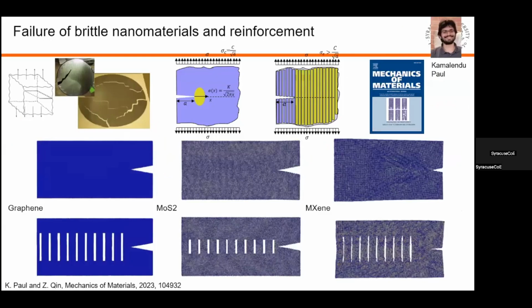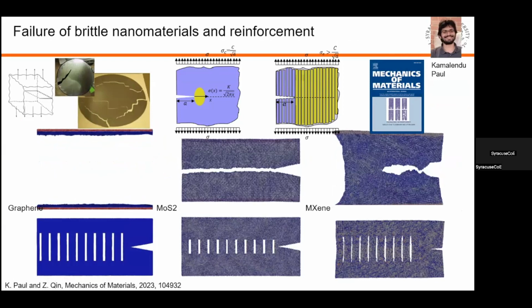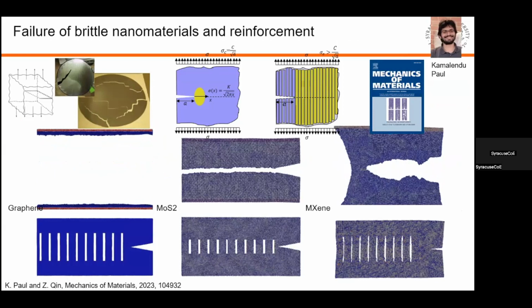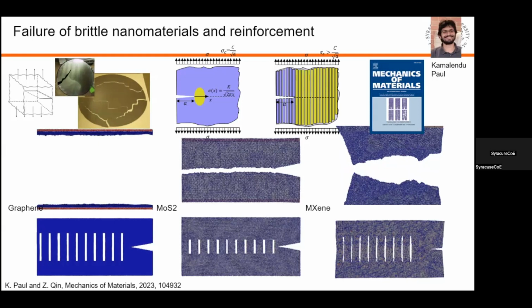This work was done by my student Kamalendu Paul. He took all those different two-dimensional materials and ran molecular dynamics simulations to study how they fracture. If you don't do anything and just take the pristine material, you see that under loading there will be a strong stress concentration at the crack tip, and once it starts to propagate, it will propagate through the entire material. MXene, being more plastic and flexible, fails later than the other two materials, which are more brittle.